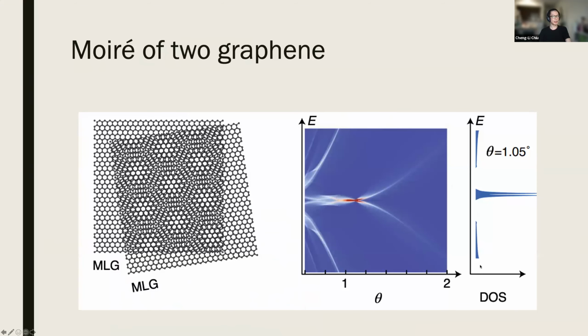So if you plot the density of states versus the energy, you find that there will be a band being isolated, or you can say it's being cut by bending your band structure, and you get a high density of states collected near the Fermi level. And we know that, for example, in BCS theory, in order to get a higher Tc, you need a higher density of states. And the same behavior can happen in other quantum phenomena when you have a large density of states around the Fermi level.